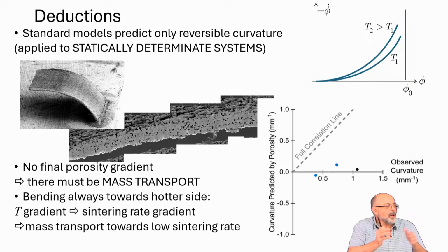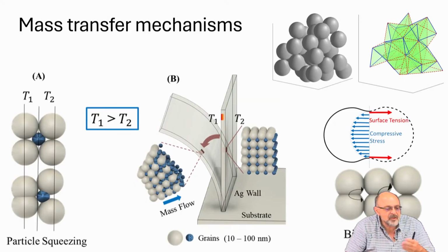So you have to transport mass, right? Because if one side is to stretch or shrink more than the other, you can either have more voids or more solid mass. And the only way to get more solid mass is to somehow transport mass. These are repeatable experiments. So our motivation here is to find out how that mass is transported.